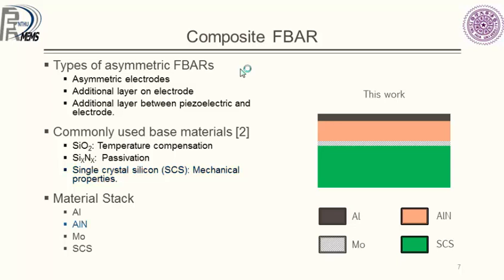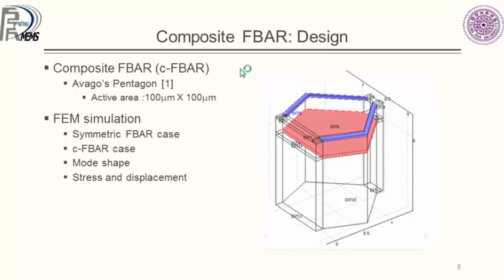The material stack for our work consists of an aluminum top electrode, an aluminum nitride piezoelectric layer, a molybdenum bottom electrode, and a single crystal silicon base layer. For our design we use Avago's pentagon shape with an active area of roughly 100 by 100 micrometers squared. The blue frame is an oxide frame resulting from DRC limitations and the red is the molybdenum bottom electrode. We performed both 2D and 3D simulations in COMSOL to verify device performance.